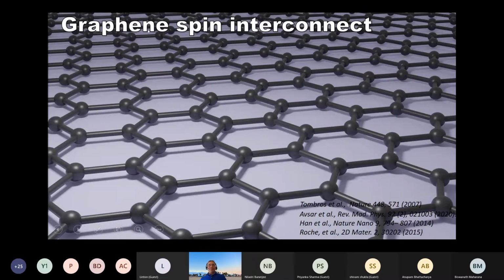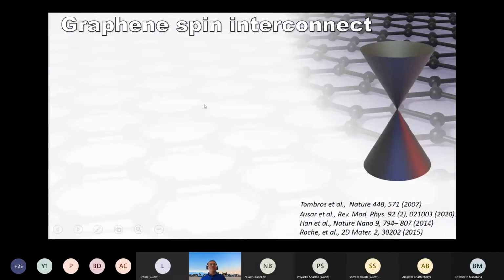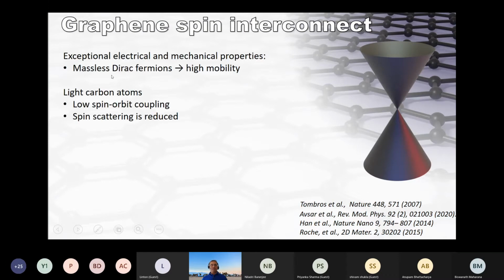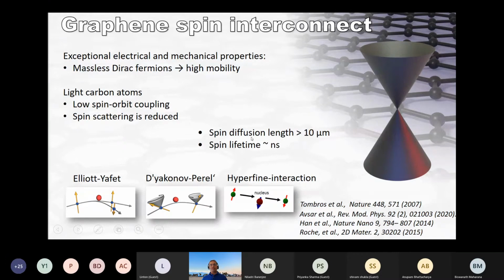So why graphene can be a good material for spin interconnect. That's the focus of this part. As you know, graphene has this Dirac band structure. This gives rise to very high electron mobility for the charge carriers. In addition, it has very low spin-orbit coupling, and so the scattering is very much reduced. This gives rise to a very long spin diffusion length, more than 10 micrometers, and spin lifetime can be nanoseconds.